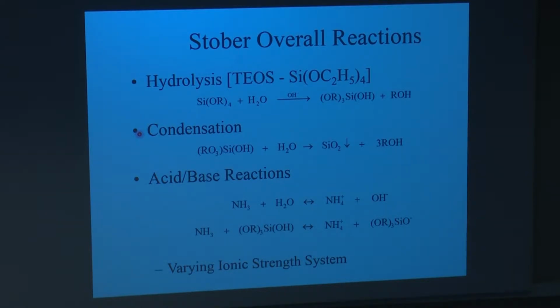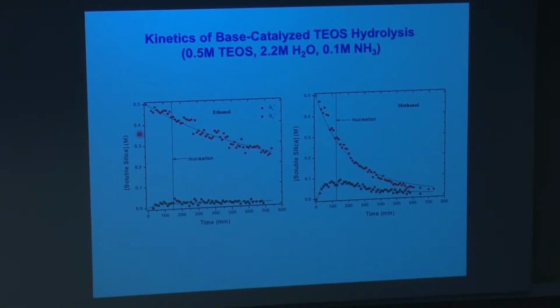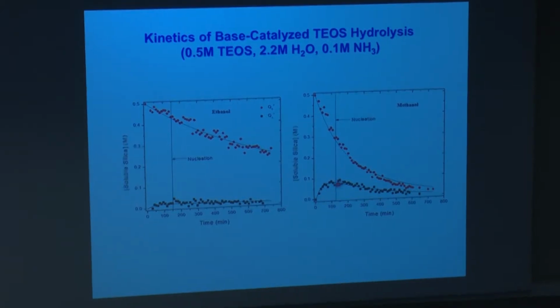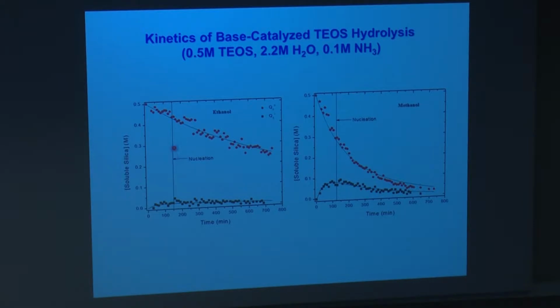the unhydrolyzed TEOS, and the disappearance of the TEOS. You can also see the first hydrolyzed monomer increases and then kind of decreases somewhat, and then we see the onset of particle formation.